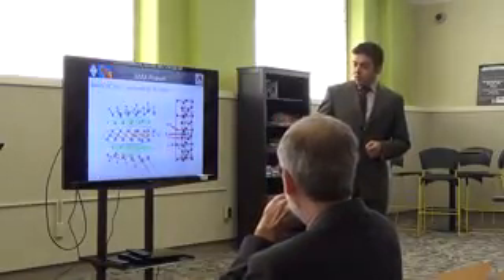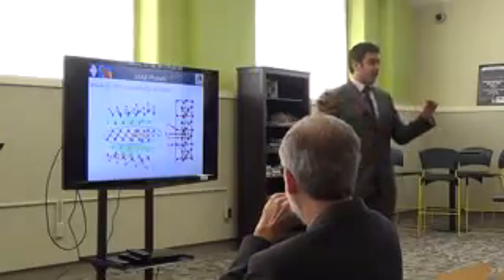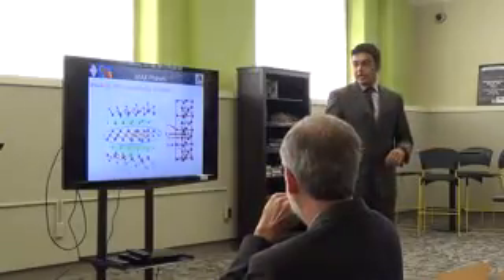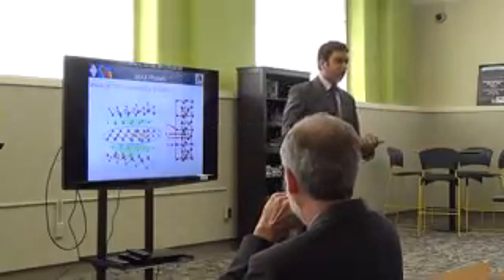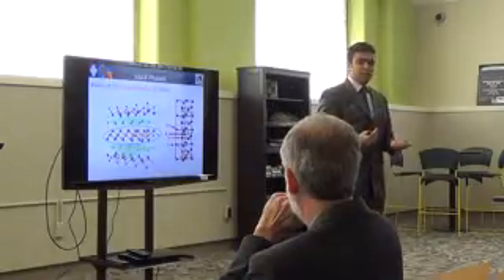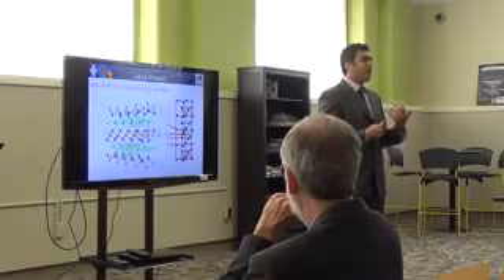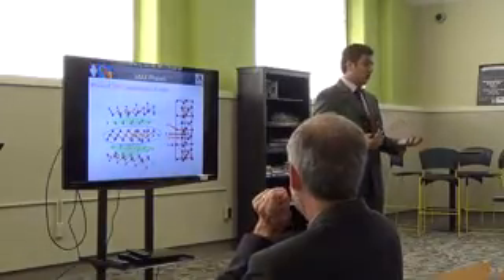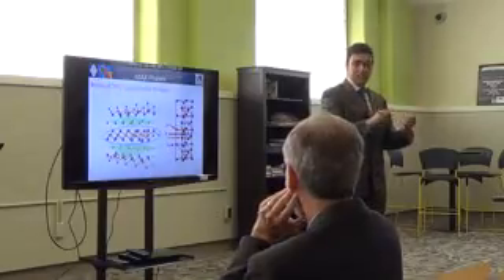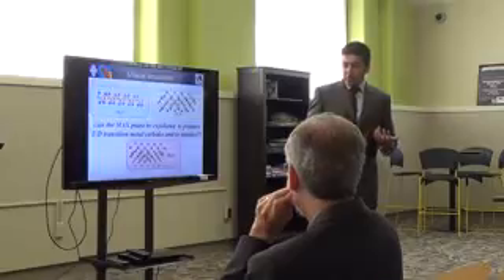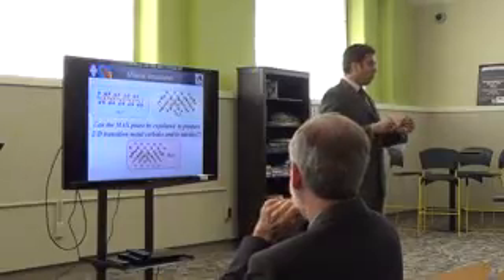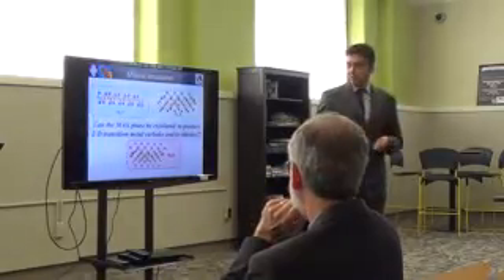So if we look closely at the MAX phase structures, we can say that they have blocks of MX interleaved with A layer. The bond between MX here is a mixture of covalent and ionic bond, whereas the bond between MX and A is metallic bond. So metallic bonds are a little bit weaker than mixed ionic covalent bonds, but they are still strong. You cannot separate them by Scotch tape. So we were trying to separate them. So can we exfoliate MAX phase and form 2D layers of transition metal carbide?